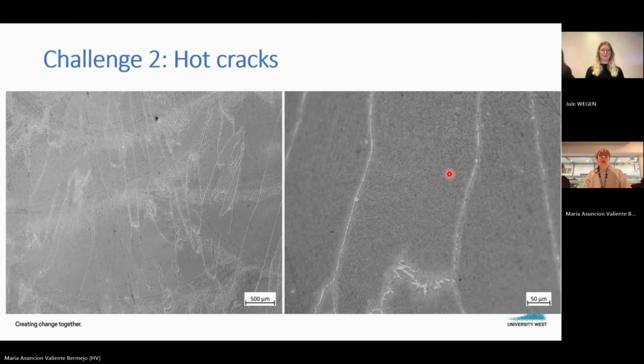And then we found another challenge, which was the hot cracks. As I showed you in the very beginning, this is the typical microstructure that we can expect when we have a very fast cooling rate: fully ferritic microstructures, where all this dark is ferrite, and then very, very thin grain boundary austenite forming here at the edges.